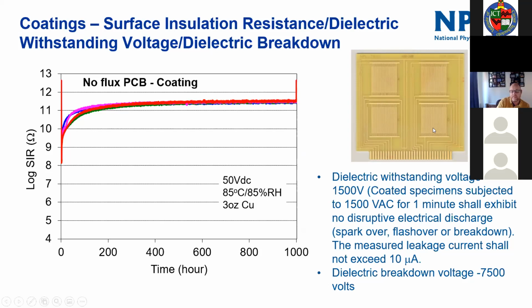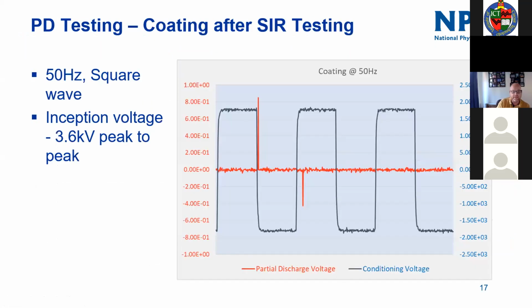If you put some solder paste underneath here and reflow before you coat it, it probably drops down to somewhere between 10 to the 9 and 10 to the 10 ohms, but you don't see, generally speaking, over a 1,000-hour test, any degradation in the system. Similarly, if you test that coating for a dielectric withstanding voltage, which is 1,500 volts AC for 1 minute, it doesn't exhibit any disruptive electrical discharge. There's no flashover, no sparkover, no breakdown. You measure the leakage current, it's less than 10 microamps, and that passes the IPC ASTM standards for coatings. If you do a dielectric breakdown voltage test on it, it'll go to 7,500 volts without too many problems at all. So it's there quite happily.